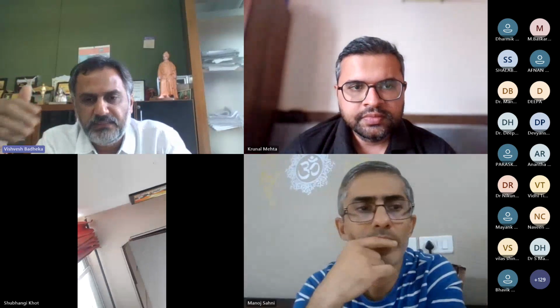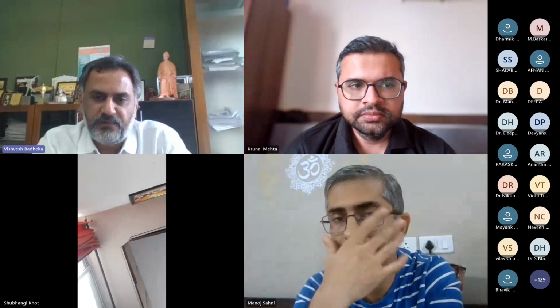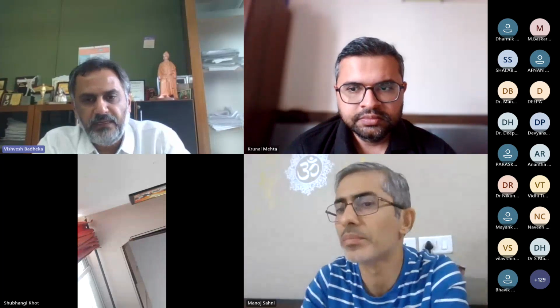Sir, may I know the amount of force or pressure applied during FSW? The downward force applied during friction stir welding depends on the material, so that value will be different for different materials. Initially, during the plunging stage, the downward force is very high. Once the plunging is over and the shoulder starts moving, the downward force stabilizes, and while ejecting, it goes down further. For soft material, what we have observed in our laboratory is that it can go close to 150 to 200 kg of downward force in the Z direction.